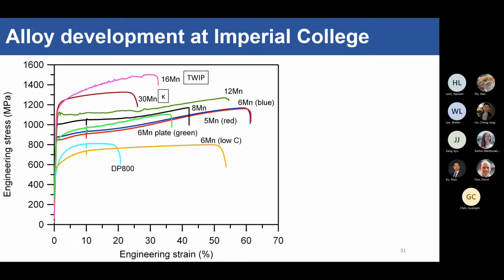But decreasing in manganese doesn't mean that we've lost any ductility. So by decreasing the manganese content, we've played around with carbon, aluminum, and silicon so that we re-optimize the TWIP plus TRIP effect, which is now largely TRIP, to give you very, very large elongations as well. So our final iteration here, this is 6 manganese low carbon, that's your Quadrolloy steel. You can see that we've got the same strength as your classical DP800, your dual phase steel. We have the same tensile strength here, but this time way more ductile and actually cheaper as well. Okay, great. So that takes me to the end of our alloy development at Imperial College.